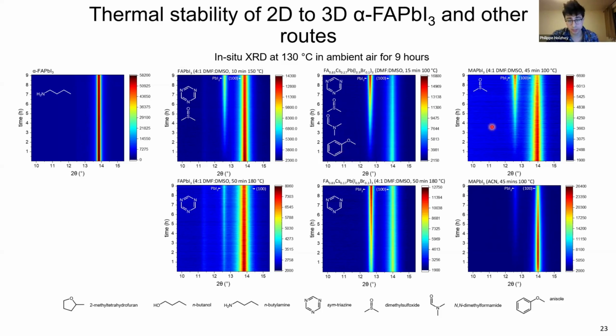And the really surprising thing, I think, in the fourth column is that also if you make MAPI, so this is not the 2D to 3D route, but another green solvent route with acetonitrile, we also get a lot higher stability for that. So we found that essentially the moment you make perovskites with a green solvent route, so no residual solvents, we find that the films are significantly more stable.